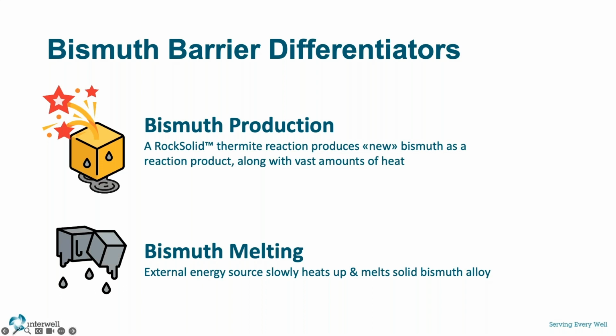We utilize a thermite reaction to produce the bismuth alloy as a reaction product. This exothermic reaction can create vast amounts of heat. The reaction temperature reaches plus or minus 3,500 degrees Celsius, more than enough heat to remove the surrounding wellbore elements at the setting depth.